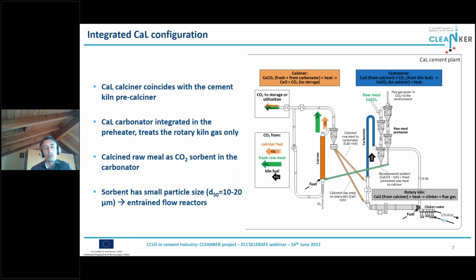So how can we apply the integrated calcium looping concept in a cement plant? First of all, we have to switch the precalciner to oxy-fuel combustion. The precalciner plays in this concept the double role of feeding the carbonator for CO2 capture and also the rotary kiln. A fraction of the material produced by the calciner is used directly for producing clinker, and a fraction is recycled to the carbonator. In this way, we produce at the calciner outlet a CO2-rich gas.